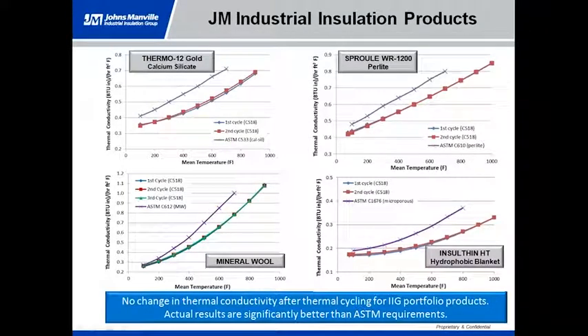To give you an example, this is what we tested, and this was done using plot testing, but again, note on each one of these plots we have the ASTM line, which is the purple line translated up from all the other lines. Now the two lines below it represent the testing, which we described earlier, where we tested each individual set point, we let everything cool, then we tested it again.